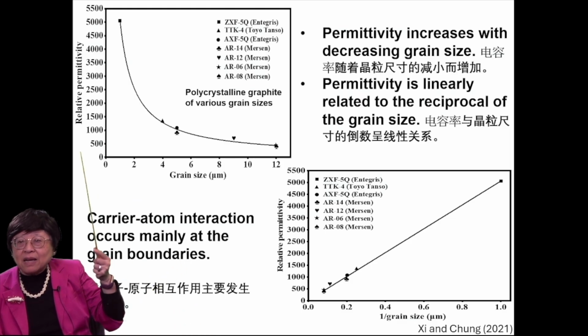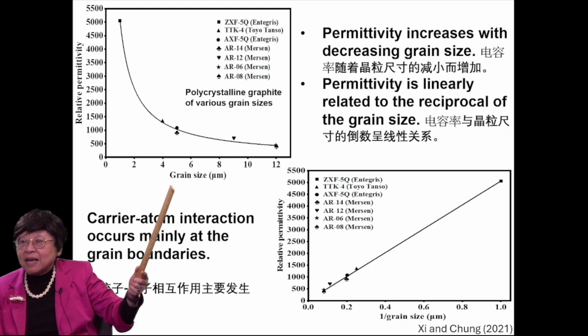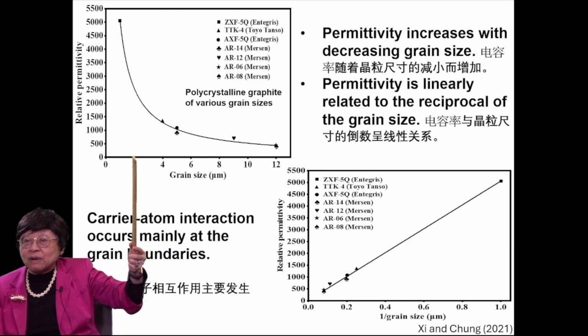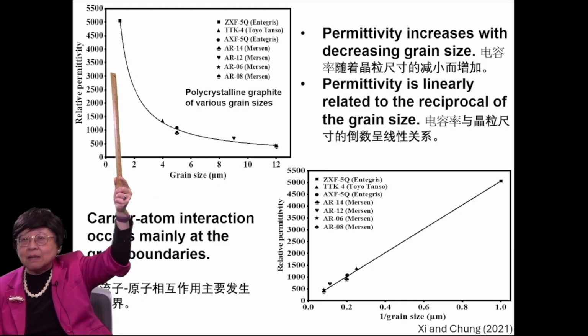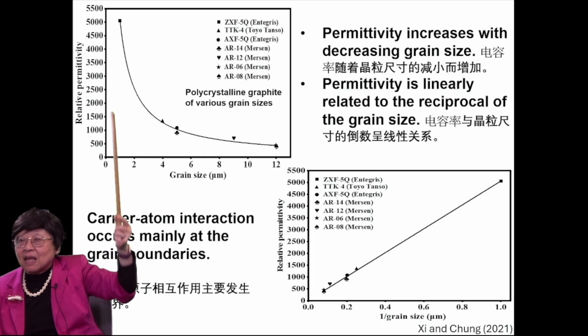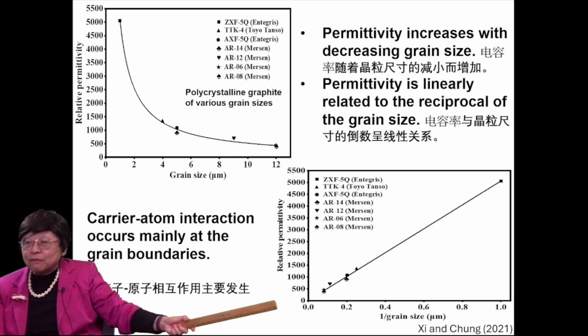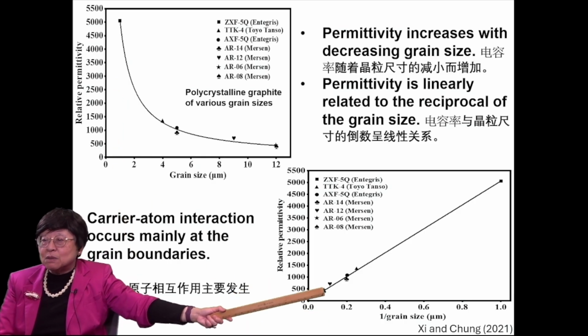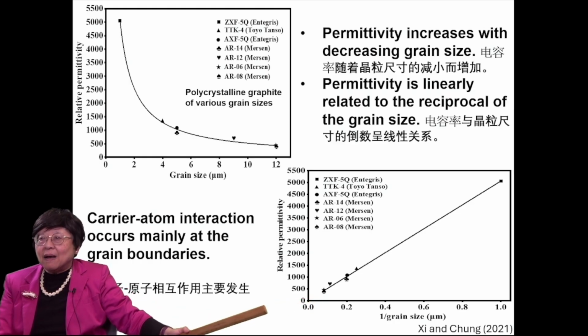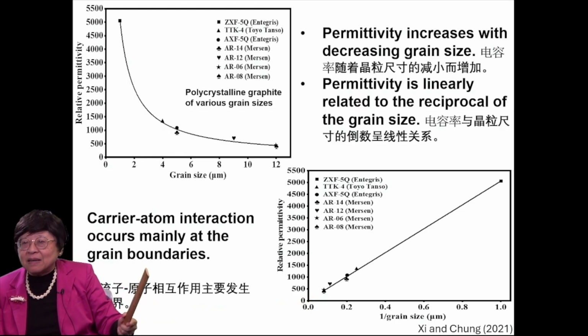This shows the relative permittivity versus grain size for polycrystalline graphite. The smaller the grain size, the higher the permittivity. And if one plots versus 1 over grain size, it is more or less linear, which means the carrier-atom interaction occurs mainly at the grain boundaries.